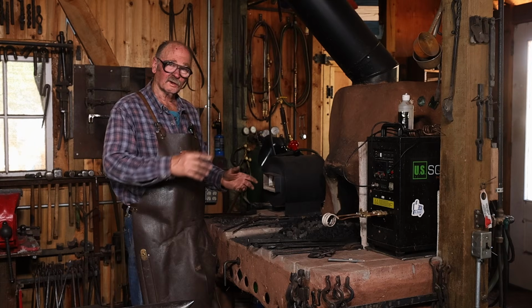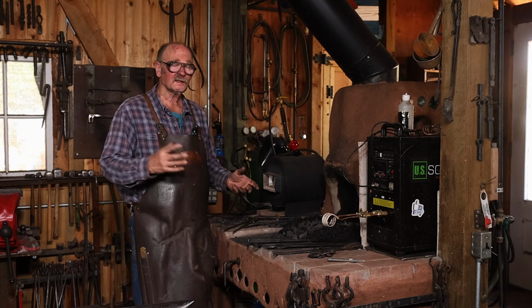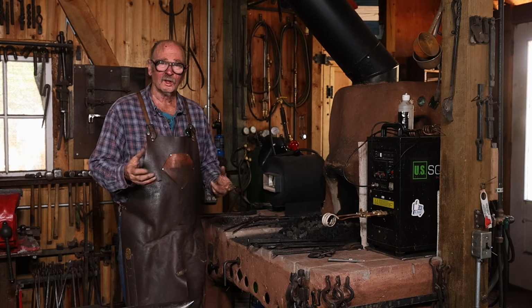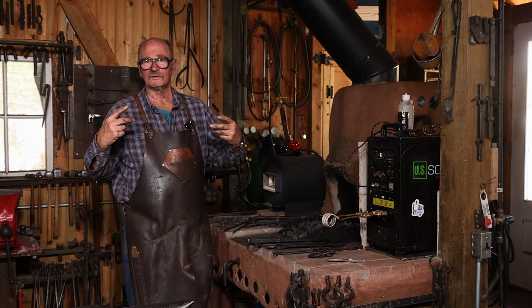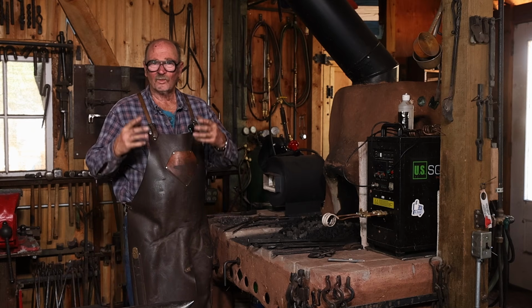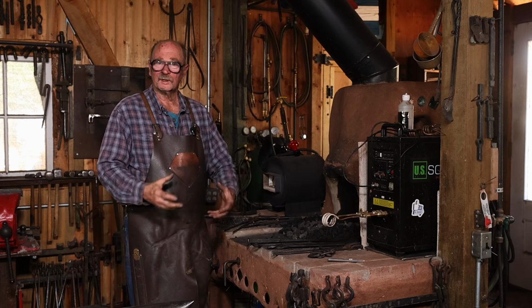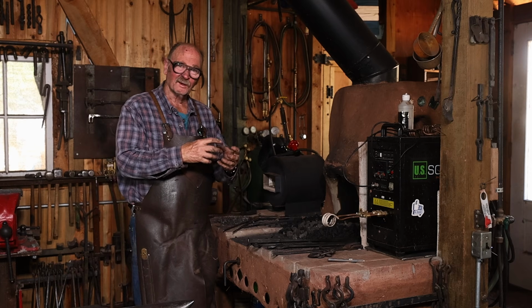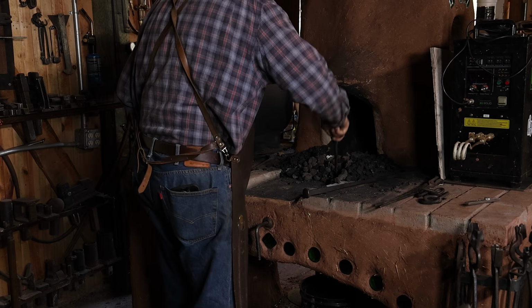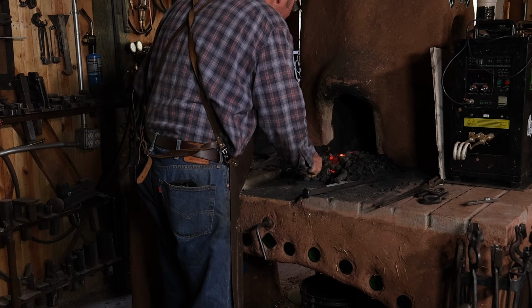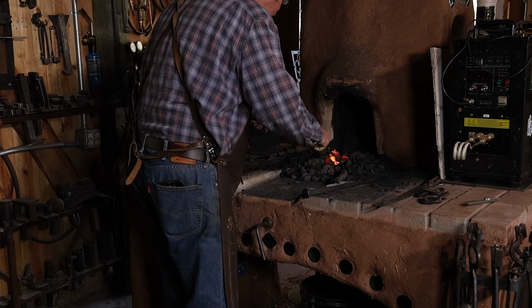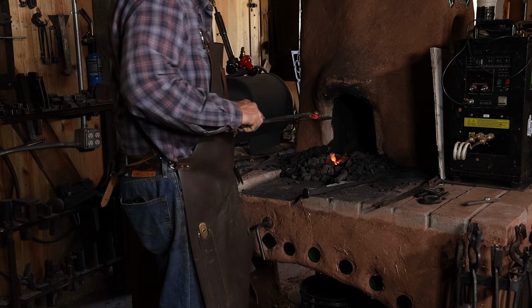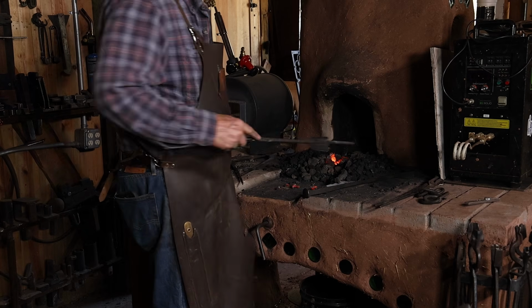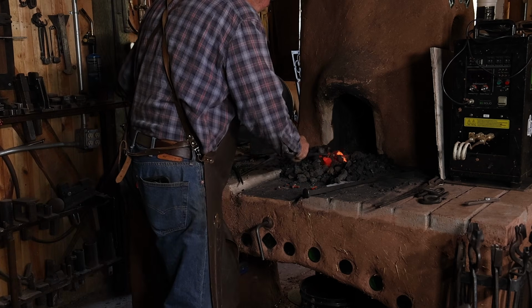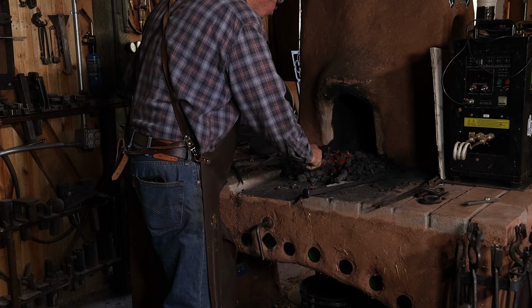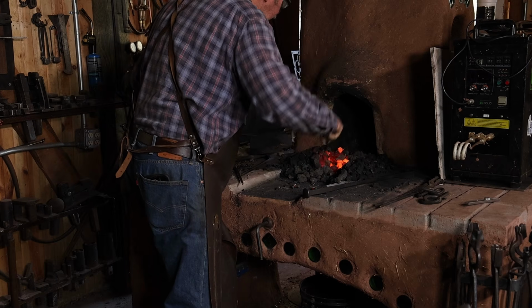Now, another enemy while you're trying to get a good heat is clinker in the fire. Clinker is all the junk that's in the coal. It's welding flux, it's scale off the material. Whatever's in there that isn't carbon to burn kind of melts down and forms a glassy substance that's called clinker. If you've been working for a while and you don't know that you've got a good clean fire, it pays to stop and clean out the clinker. Now, I don't have very much clinker in this fire. It's a fairly fresh fire, but there is a little bit from doing that one side of the tongs.